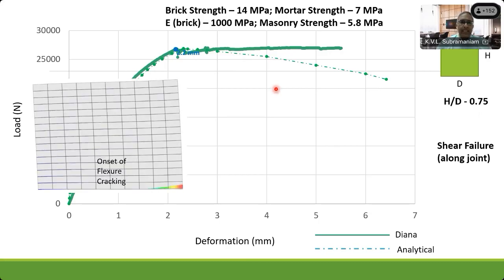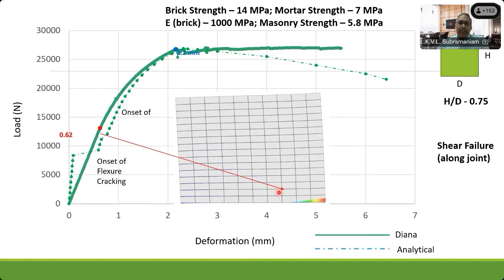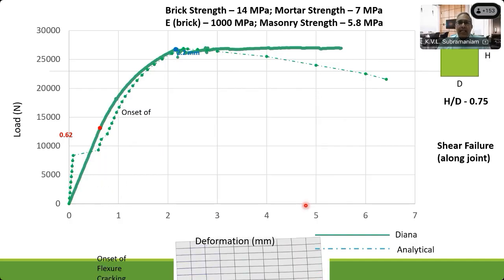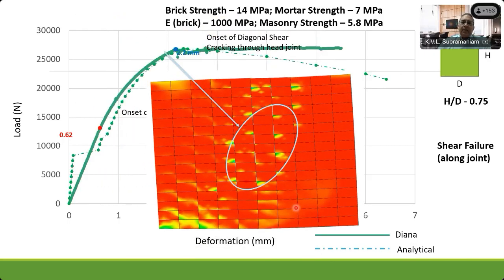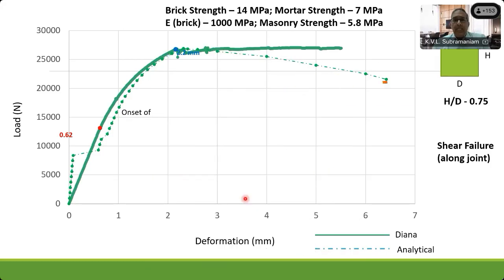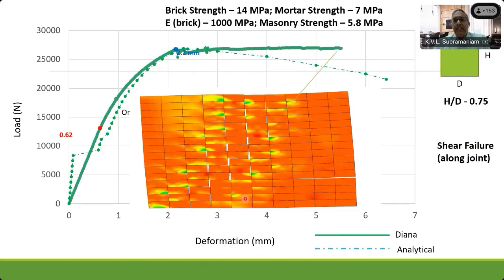And we can also predict the failure in this masonry unit, where in this particular case, it fails in flexure at one side, and with continued loading, we can actually see when the diagonal crack would start to form. It's a squat wall that basically fails in shear. A shear crack forms through this. We can now simulate the damage that happens in the brick as I push the wall all the way up to failure, where the failure of the wall happens because of this shear diagonal cracking that forms in the masonry.